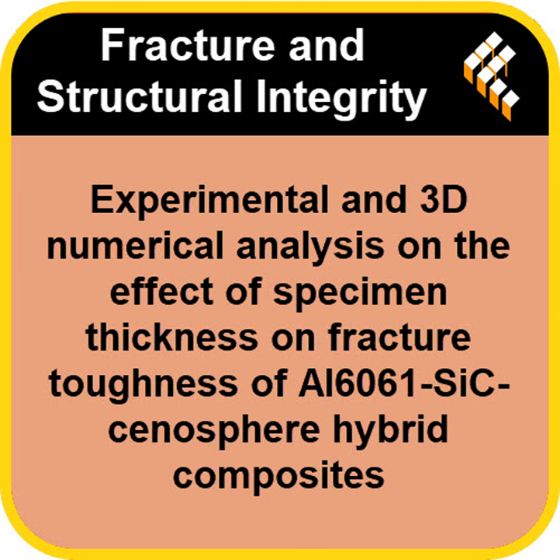And second, the optimal recipe, the best balance for high toughness and good lightweight properties, is the blend with 3 wt% SiC and 6 wt% cenosphere. Pushing the cenosphere content higher to 9 wt% is actually counterproductive. You sacrifice strength because of that destructive particle clumping during manufacturing, and you don't gain that much more lightness. 6% is the sweet spot they found. So B/W equals 0.5 and 6% cenospheres.